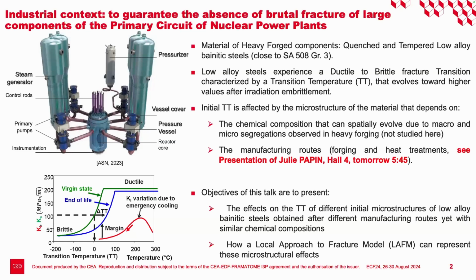These steels experience a ductile to brittle fracture toughness transition, characterized by its reference transition temperature, as you can see on the green curve here. And as for the material of the reactor pressure vessels, this transition temperature shifts towards larger temperatures as years go by because of irradiation and embrittlement, thus reducing the margin that you have in design. If you imagine that you have a pressurized thermal shock, for instance, you have the margin between the crack resistance here and the loading here.